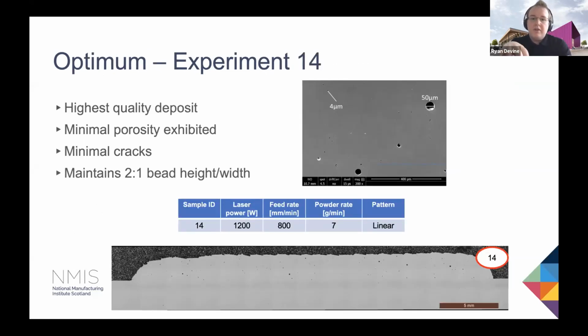From this, we saw that experimental run number 14 was the highest performing sample. It gave minimal porosity, which was ideal, and minimal cracking as well. It also maintained roughly the 2 to 1 ratio that we were aiming for. So this laid out the parameter set that we should be using when it comes to actually working on the